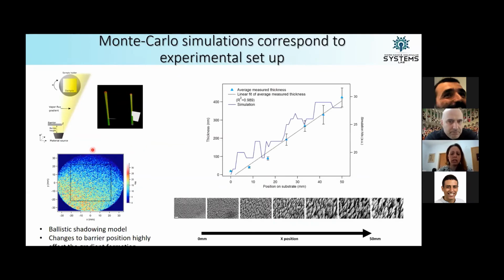And we were actually able to achieve quite a nice gradient in the vapor flux, which led us to linear thickness changes, which are quite important because then we know that one area we have a little bit of material and in the other area we have a lot of material. And this of course depends on the vapor flux as well as the alpha angle that we use in the